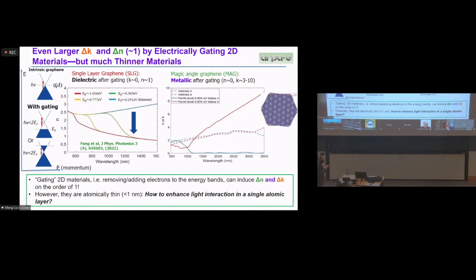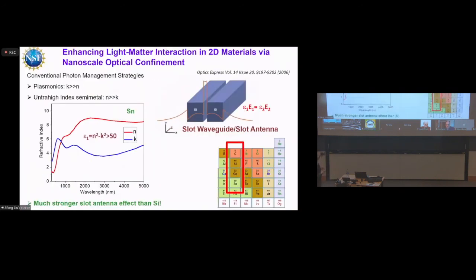And Tao found that if you do this trick on the magic angle graphene, you're really converting this to a kind of metal, because your K is really big and your N is pretty small after gating. So it's the opposite compared to the case of single layer graphene, where you're actually changing from absorbing to non-absorbing. That means a semi-metal changes to a dielectric. So they work in opposite ways. So he was considering putting this together synergistically. And that actually builds upon our previous work of enhancing the light absorption in single layer graphene.